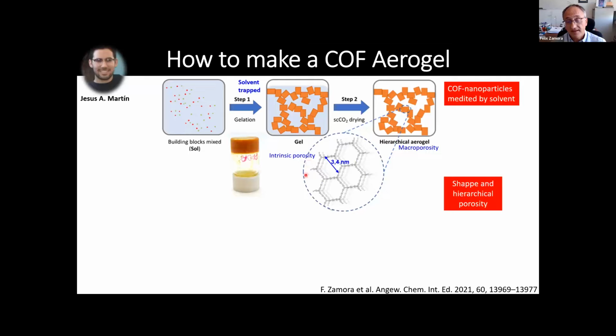And then we decided to do the following. The gel is based on the aggregation of these nanoparticles of COFs, okay? So in here, you trap the solvent, but you have kind of a macro porosity that is plenty of solvent. So the idea was, okay, let's try to remove the solvent, trying to retain the morphology of the gel, to pass from the gel to the aerogel.